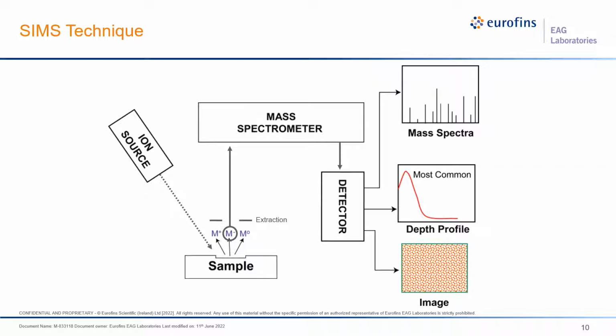And then the selected mass is impinged on the detector, and we can display the data in a number of ways. We can simply take a mass spectra to determine what is present. We can obtain an XY ion image, a spatially resolved image of the location of the element of interest. But most often we do a depth profile, and that is done by monitoring the masses of interest as the sputtering continues. And as you sputter, the surface recedes into the bulk. So if you monitor species with respect to sputtering time, it naturally generates a depth profile, which is the distribution of the elements of interest with respect to depth.